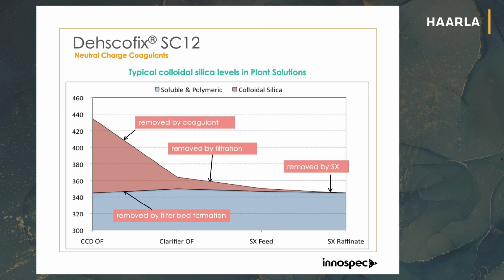Just to be absolutely clear, we make a product which is the Dehscofix SC12, and we did this sort of chart, and you can see how the colloidal silica, or the insoluble silica, decreases through the process. The soluble silica is not affected. It stays constant. But it's that insoluble silica that's the problem. That's what you really need to get out of your process.